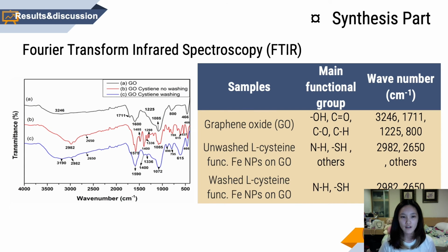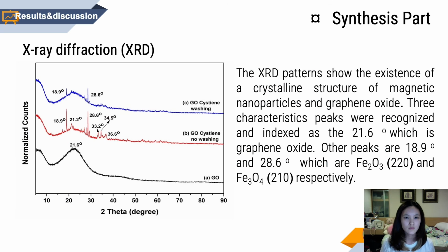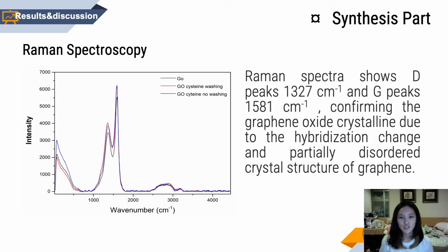From the FTIR result, the peaks can confirm many functional groups from graphene oxide and also from L-cysteine, such as the amine group and sulfide group. The XRD peaks can confirm a crystalline structure of both iron nanoparticles and graphene oxide. The D peak and G peak from Raman spectroscopy show the crystal structure of graphene.